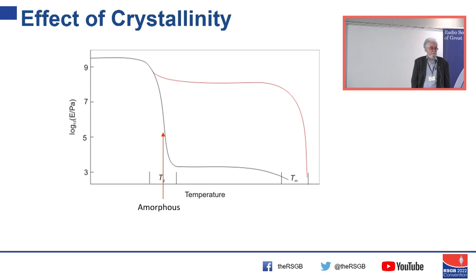That bottom sketch there is the amorphous curve. The red one is the curve that you'd get for a crystalline material. Below the glass transition, it doesn't matter. The amorphous material, the soft material in this partly crystalline structure, is still rigid. It's still frozen, glassy, and rigid. So everything is just the same.